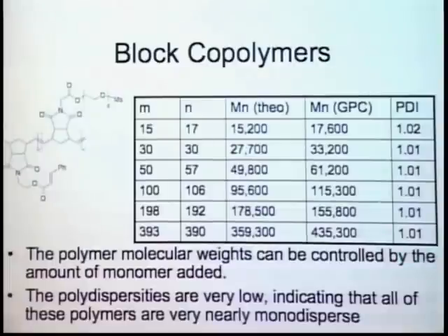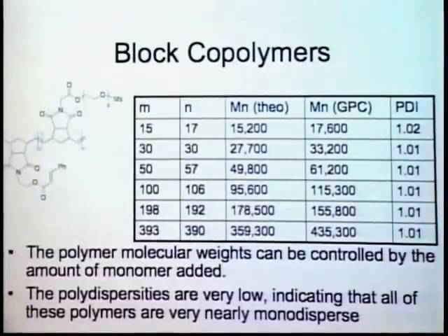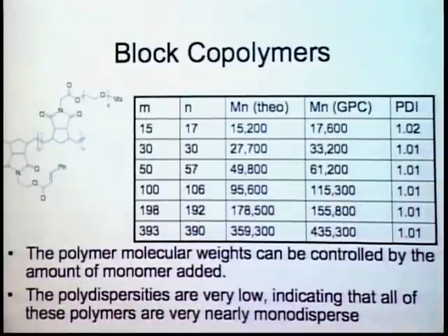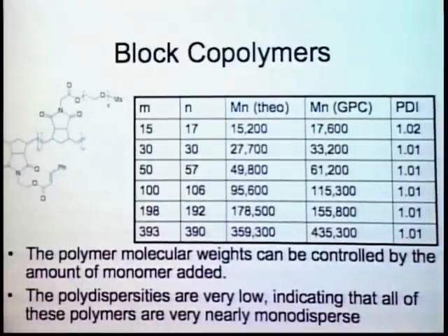You can see the PDIs are well below 1.1. Okay, we can control the molecular weights very precisely. Polydispersities are really low. So this system works out quite nicely.